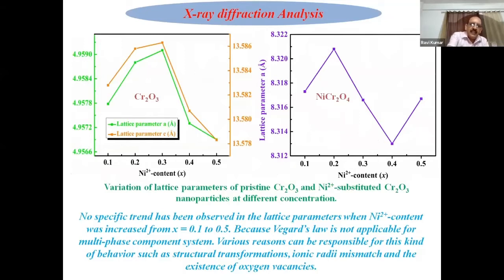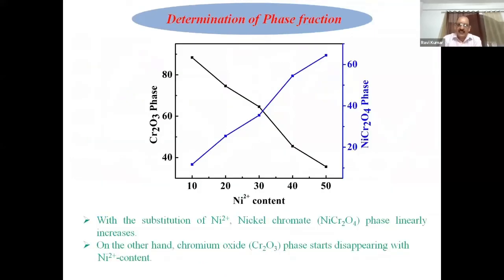You have a lattice parameter, C and A. Then for this lattice parameter, you can calculate for that phase with the concentration, and then you can see how the phase separation is there, how the chromium oxide phase and the nickel chromium spinel phase, the rhombohedral phase and the spinel phase, are varying.